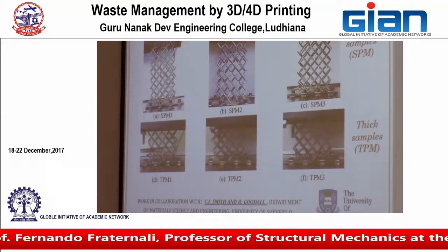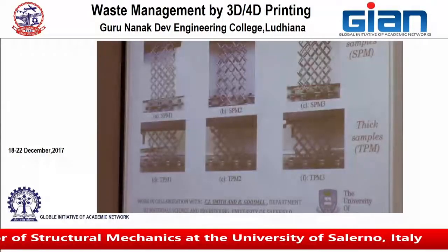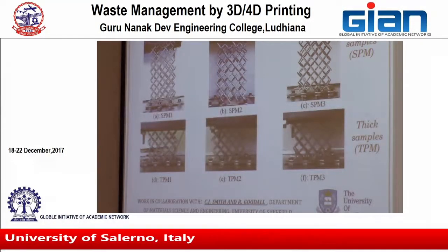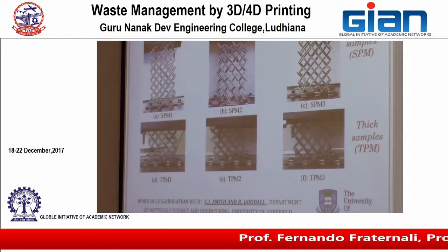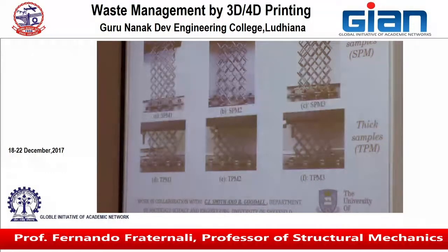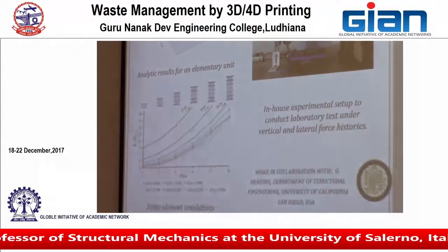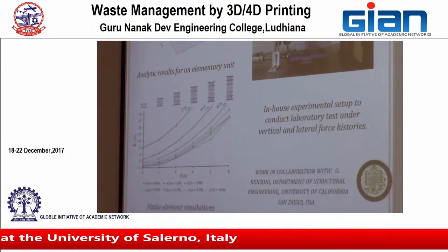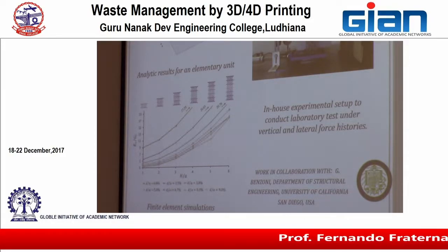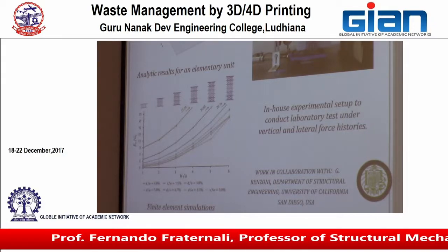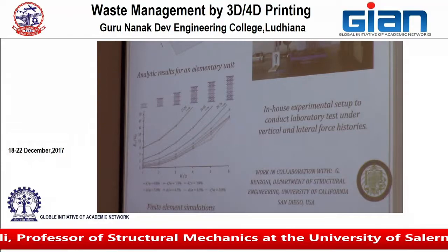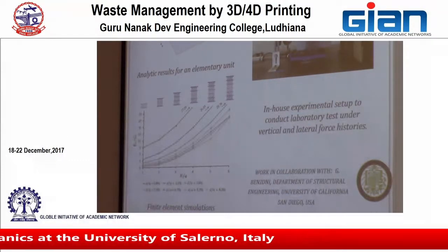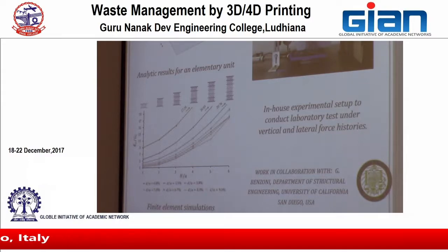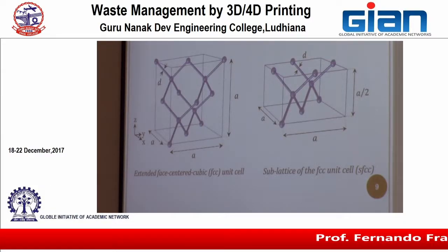Those are FCC samples, while SFCC are the ones that are obtained by replicating 1/2 of the unit cell in the horizontal plane and adding stiffening plates over the vertical axis. And we have tested them at the University of California, San Diego as candidate isolators, and we have also run some computational simulations of the response obtained by adding more and more layers. And this was an introduction.